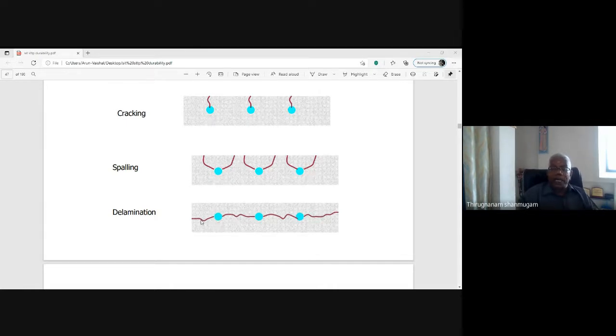So once the cracks have formed, delamination of the cover concrete takes place completely, exposing the steel reinforcement. This is the bottom of a roof slab, with the steel reinforcements completely exposed, and the rusted steel reinforcement. The cover concrete is completely spalled off. There is no cover concrete at all.